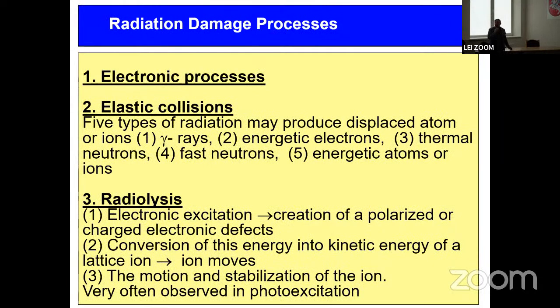So, radiation damage processes. In most of the materials, defects are created by particle radiation, by neutrons, by ions, protons. But in the case of, for example, gamma or X-ray radiation, in most of the materials there is only a distribution of electron-hole pairs, so there is no creation of new vacancies and new interstitials. So in this case, the structure and properties are not changed, and only in a few cases, so-called reliability is important.